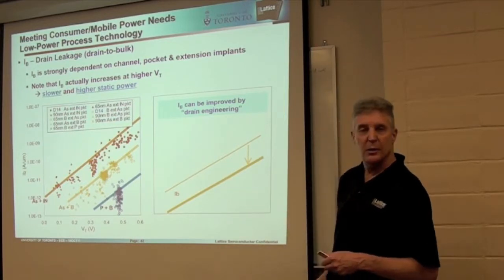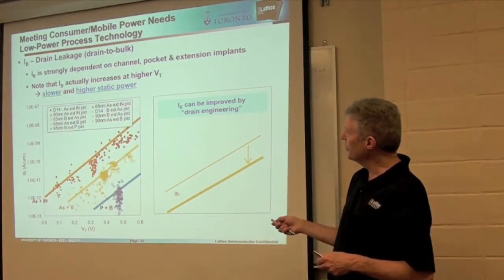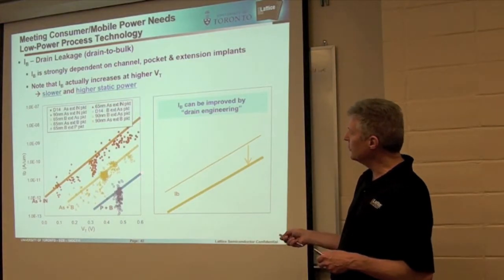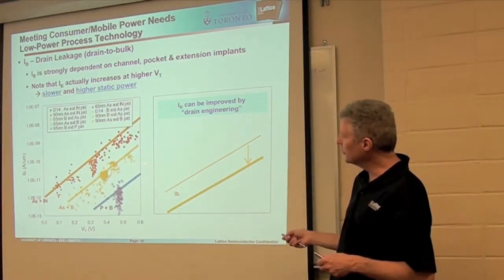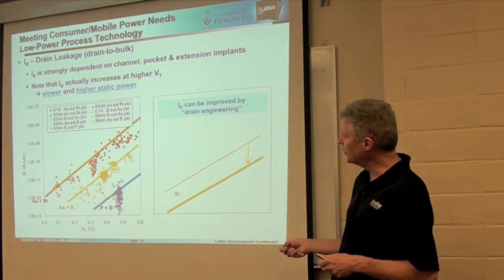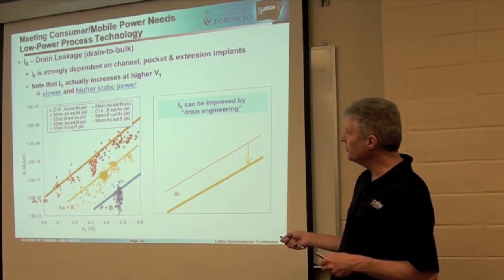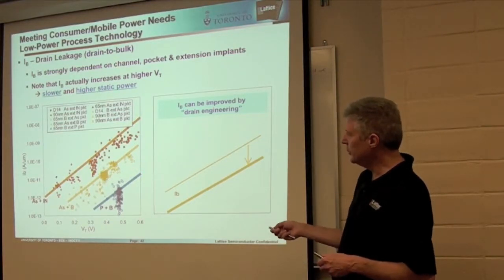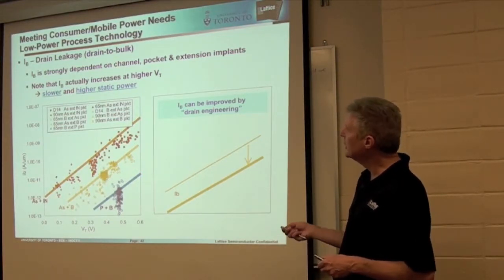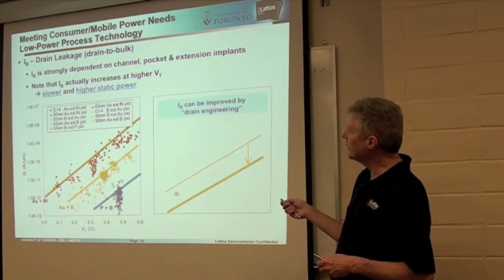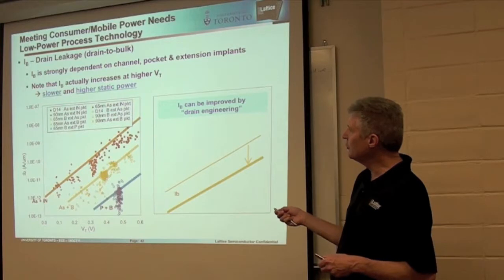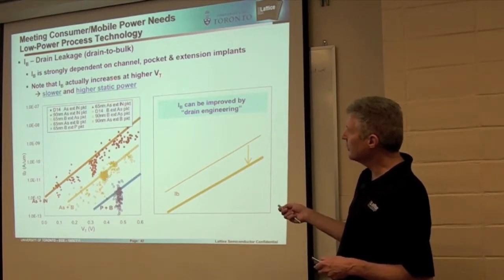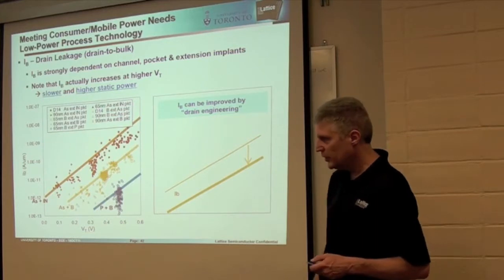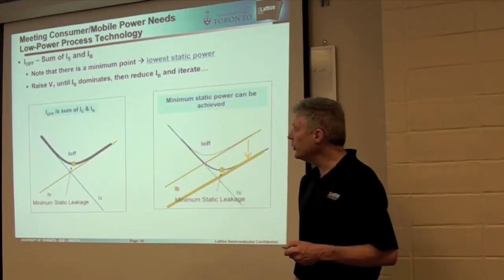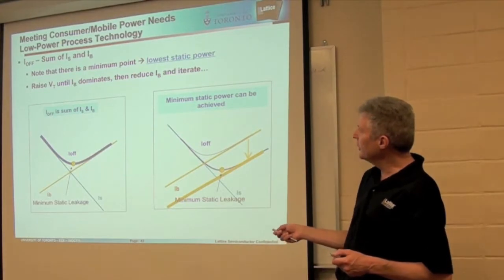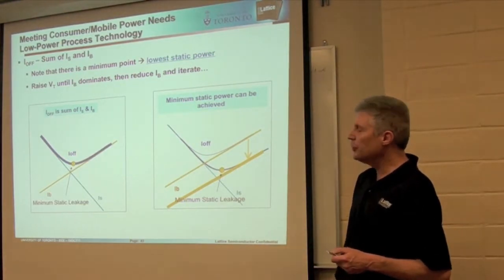The drain leakage, interestingly, actually increases at higher threshold voltage. So this is a number of different process technologies, but the basic trend is increasing threshold voltage will actually increase the leakage current as well. So that's a bad thing. This is really bad because at higher threshold voltages you not only get slower, but you get higher static power. You slow down because of the high threshold voltage, and you get higher static power because of this drain leakage characteristic. So when you put those two together, you actually find there is a reasonable minimum when you combine those.